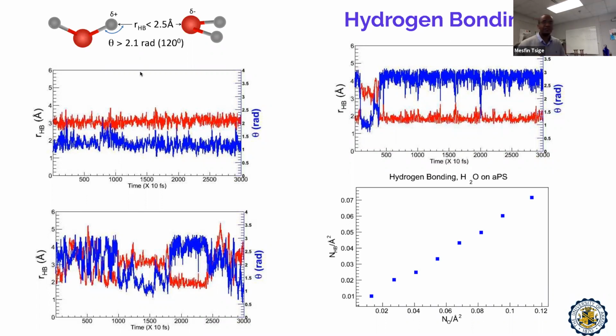So how do we characterize hydrogen bonding? The usual approach is, if I have two water molecules, such that the oxygen of one water molecule is within a distance of 2.5 angstrom or less from another hydrogen atom of another water molecule, and the OHO of that one makes an angle greater than 120 degrees, we say they form hydrogen bonding. This is a geometric approach. There is a geometric approach and energetic approach. Both match very well. So we have followed all possible hydrogen bonding in our system.